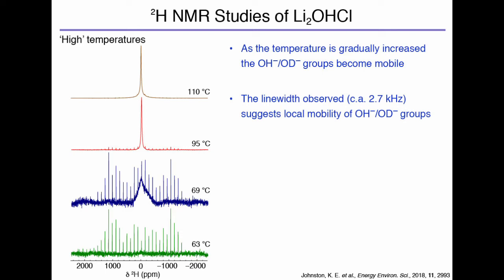Now, you'll see my bottom temperature here, so I'm looking at 63, 69, 95, and 110 degrees C. Okay? At 63 degrees C, the spectrum looks pretty much identical to what we're seeing at minus 19 and 33 degrees C. It hasn't changed. But we're at 63, so it's clearly undergone that phase transition that says it's a superionic conductor at that point. But the protons are still static.